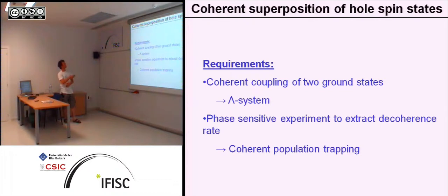Okay. So now to the last topic, and that's the coherent superposition of quantum dot states, and in our case the hole spin states. So how do we create a coherent superposition of 2 ground states? So you need a coupling mechanism between both states, which is coherent, so it cannot involve transition to another excited state, as we had in the experiment before, where we had 4 levels, and the excited level is coupled by the electron spin, spin up or spin down.